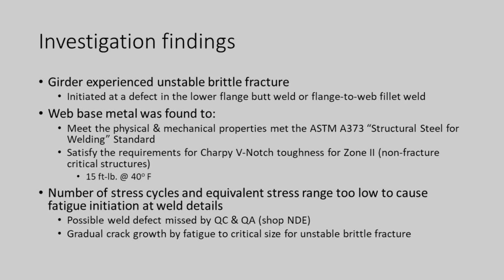We think there was gradual growth of this weld flaw by fatigue to critical size for unstable brittle fracture that ended up basically almost parting the entire girder. One other thing too, if you find a weld defect on a bridge, based on this assumption that things can be missed if people aren't doing right or paying attention, if you find one defect, more than a random possibility, there may be something else lurking about in the steel there.